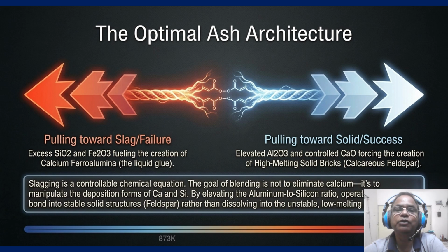Second is dilute the aggravators. So blend with coal specifically chosen to dilute total silica and keep iron strictly under the 18% threshold. And point number 3, armor with the alumina, where we introduce high alumina or blended coals to expand the thermal stability window. So pushing alumina forces the ash to remain in a manageable semi-solid state all the way through the critical 1473 to 1673 Kelvin